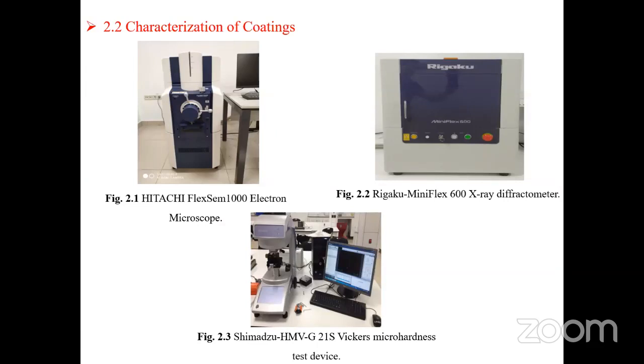Surface morphologies of the electrodeposited nanocomposite coatings were studied by scanning electron microscope, Hitachi FlexSem1000. Also, how the grain structure changed under different conditions was examined. The phase and structural analyses were conducted by the X-ray diffraction method using a Rigaku MiniFlex 600 X-ray diffractometer. The full width at half maximum values of X-ray diffraction were utilized to calculate grain size by using the Debye-Scherrer equation. The microhardness of the nanocomposite coatings was measured using a Vickers microhardness test device, carrying a load of 50 gram for 10 seconds. At least 10 measurements were applied and average values were taken as reference.